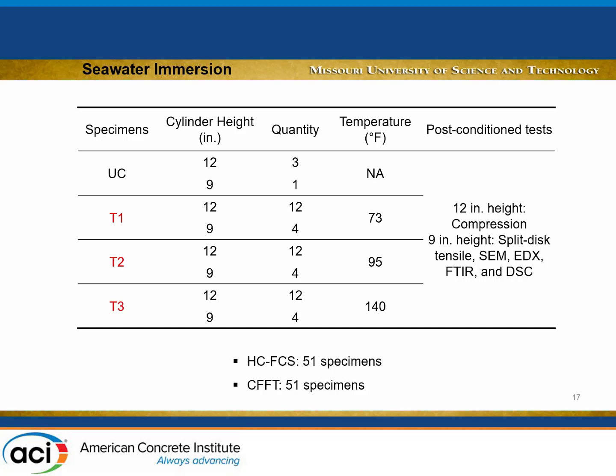So in total, we have 51 specimens for the hollow core fiber concrete steel, another 51 specimens for the concrete filled fiber tube. For those, we go every 3 months for each tank, and we take some specimens and we test them in compression. We run the microstructure analysis on all of them, so we can track over the year how the strength degrades. So for each tank, we tested specimens at 4 different periods. During the presentation here, we're going to call them B1, B2, B3, B4.